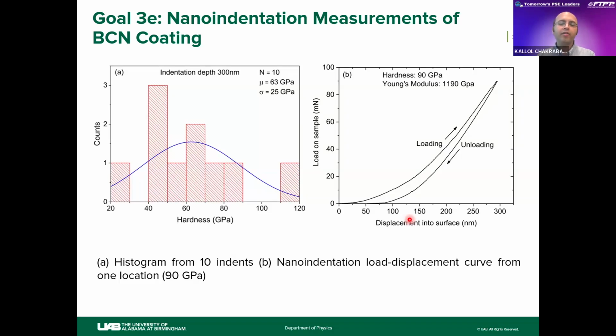According to the nano-indentation, the mean hardness was 63 GPa, which is way higher than the superhard threshold of 40 GPa, so our sample is a superhard material. Most of the data points are above the 60 GPa landmark, and one data point was as high as 90 GPa.